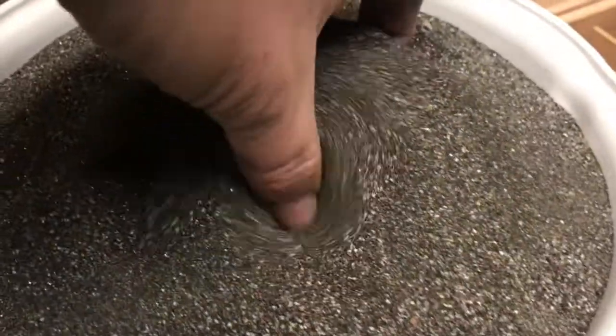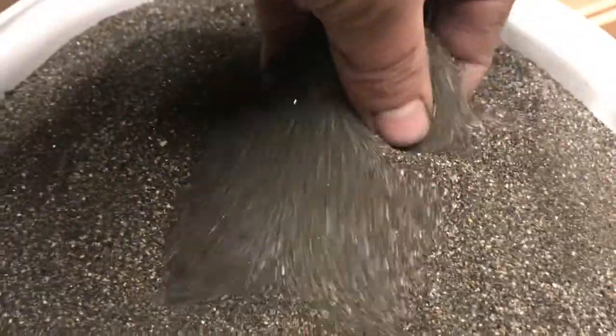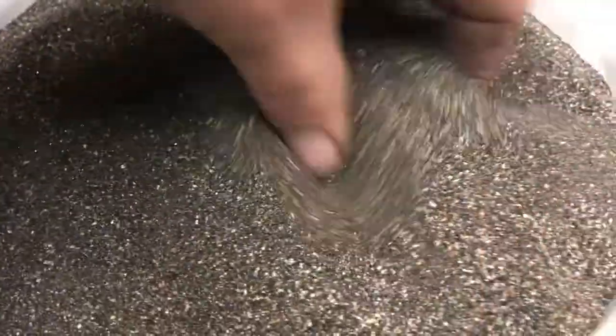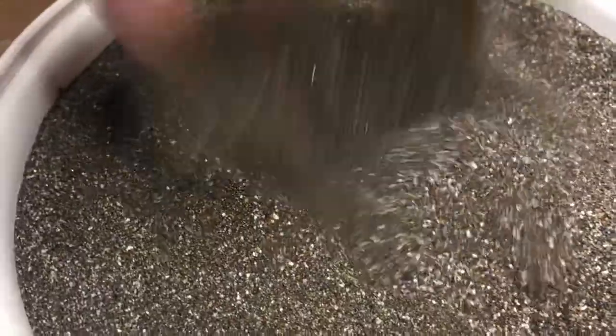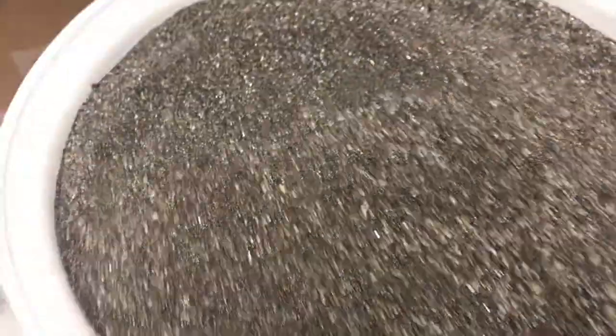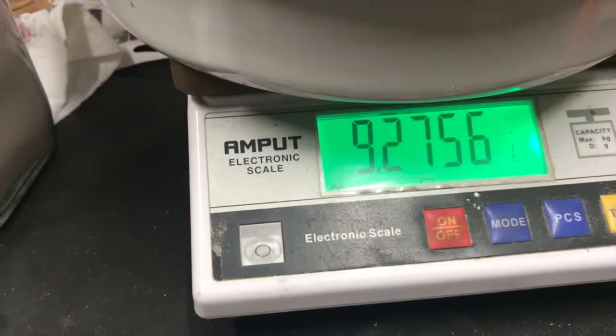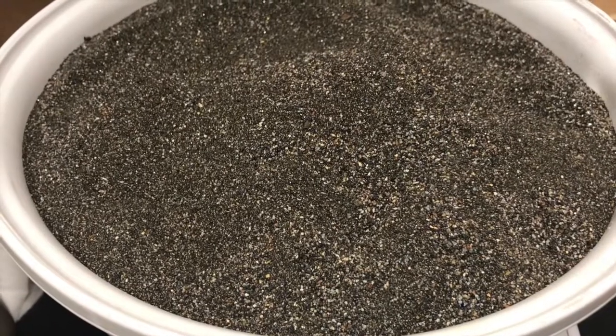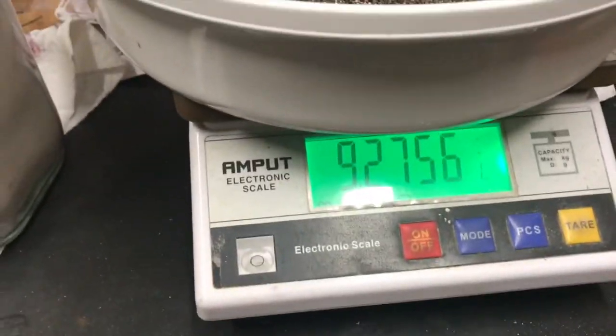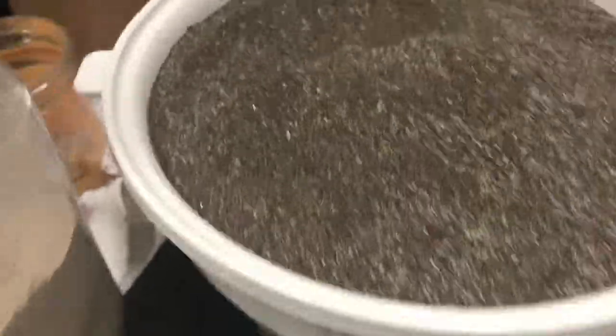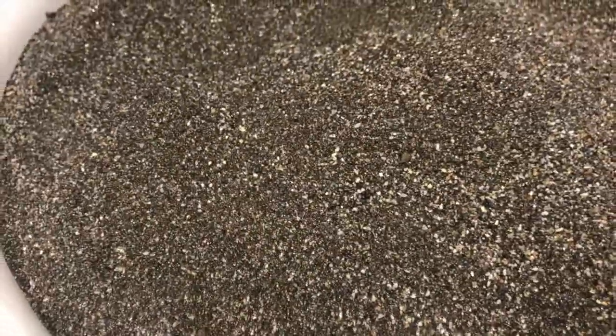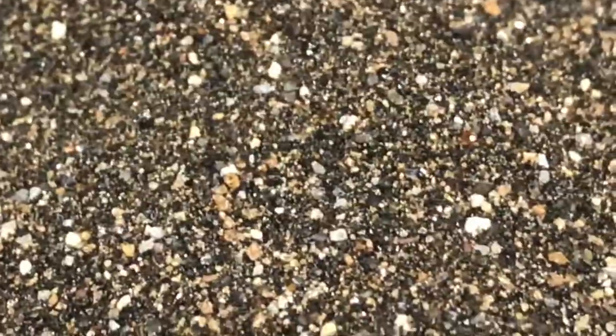Now, there were some concentrates that were fine. They didn't have as much coarse lead in it, so there wasn't as much gold. This was concentrated on my shaker table so that excess propane wouldn't have to be used to do multiple smelts, because the gold content was actually fairly low per pound. But we did end up getting about an ounce of metal out of all of this in the end.